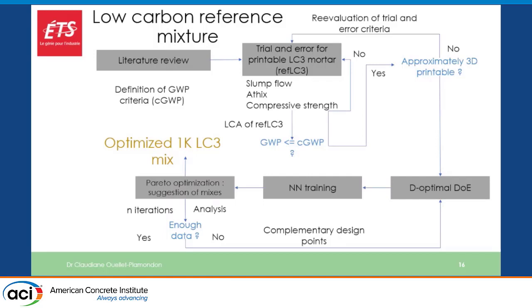Now let's see how we're looking at the low carbon reference mixture. I think we're very inspired by the LC3, so it's a mixture of cement, limestone, metakaolin, and calcined clays. So, well, there's different ways to look at it. And then we have a set of criteria. So we have one with the global warming potential, in terms of kilograms CO2 equivalent per kilogram of concrete. And then from the 3D printing literature, we know that we have criteria on the slump, on the thixotropy, and the compressive strength. And then we do a rather iterative design, and we are using the D-optimal design of experiment to try to get as much information from a limited amount of experiments. And then we are combining experimental method and some machine learning algorithm to go faster. And then, the work is ongoing.